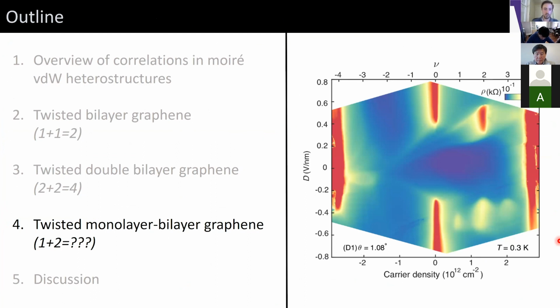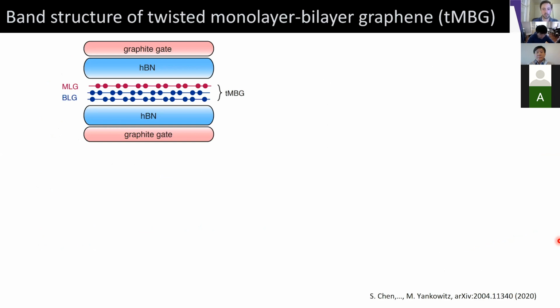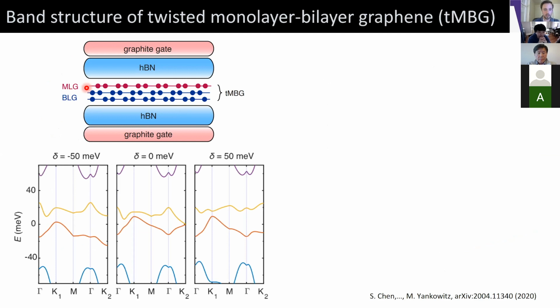And basically removing one of these graphene layers now and looking at a twisted monolayer-bilayer graphene heterostructure. All right, so the name of the game is pretty similar. We make these encapsulated structures now of a bilayer graphene and a monolayer graphene with a twist angle of around 1 degree. And again, we can calculate the band structure. We think that we understand a lot of things from the single particle level in the same way that we did in twisted double bilayer graphene.